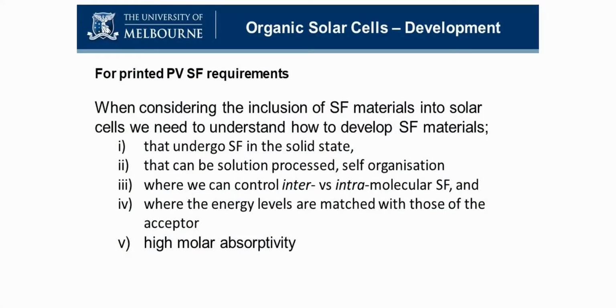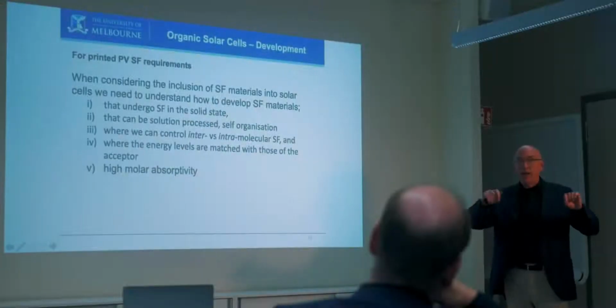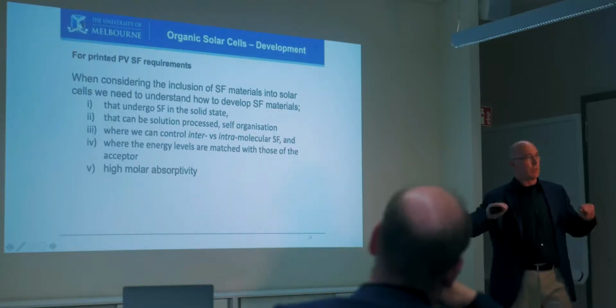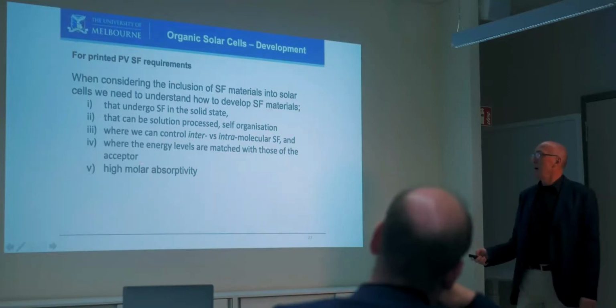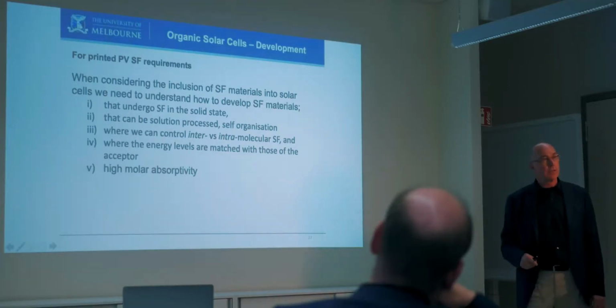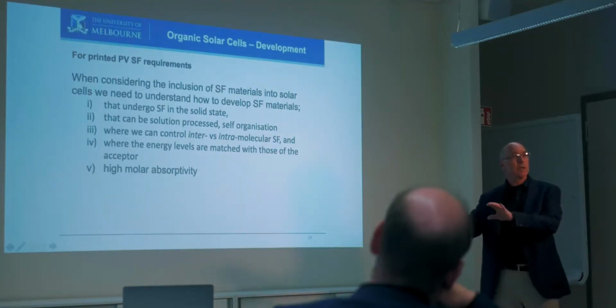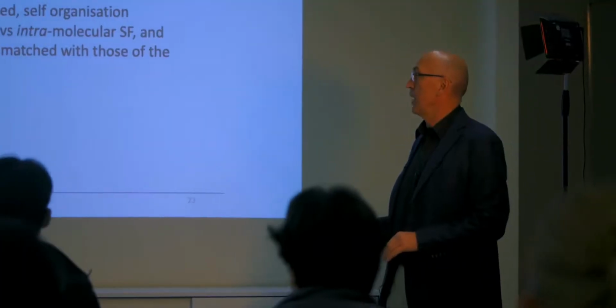So when I came into this work a number of years ago with Cigar, we basically said, what do we need to change? And so we said, okay, we want to ensure that these materials undergo singlet fission in the solid state. We want to be able to control them, solution process, so we have to have them self-assemble so we can control how they assemble so we don't get different polymorphs. We want to be able to control with our inter or intra, so if we have a bridge that's intramolecular, because we have these two molecules that we're going to put these triplets on in the same molecule, and we want to be able to energy match the singlet fission material to the underlying solar cell. And we also want high molar absorptivity. We want the actual material to absorb a lot of light for a thin film.